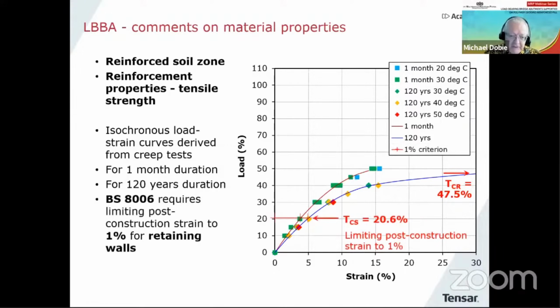And then what BS 8006 requires is that the post-construction strain should be limited to 1% during working life or post-construction. Now, it is assumed that post-construction is from about a month to the end of design life. In other words, between those two curves that you can see. So if you look at the distance between the curves and you find the point where it's 1%, where the strain axis is in percent along the bottom, then in this particular case, TCS is about 20.6% of the tensile strength of the material. You can see TCR also on this diagram. I've added that as well, so you can see how they compare.